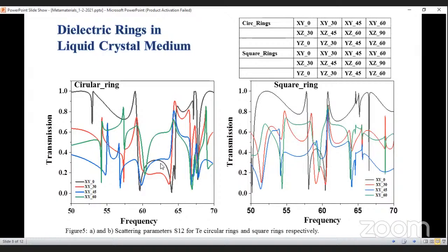Here we used liquid crystal as a medium, which is an anisotropic medium. Here we studied the scattering parameters as a function of angle. We rotate the liquid crystal angles at 0, 30, 45, 60 and 90 degrees with the x-y, x-z and y-z planes. These are the input parameters in the CST software, and we check the response of tellurium structures in different orientations of the liquid crystal medium.